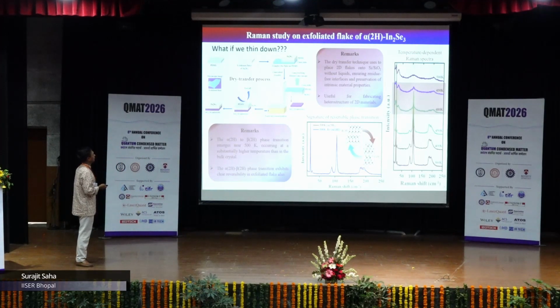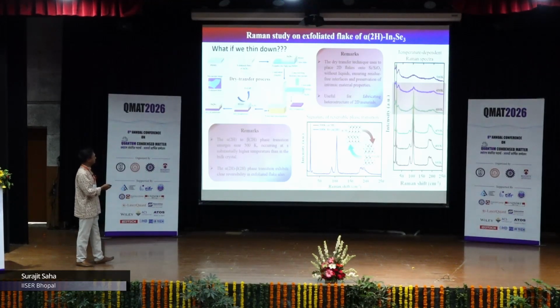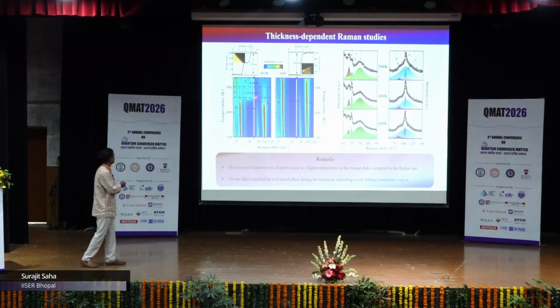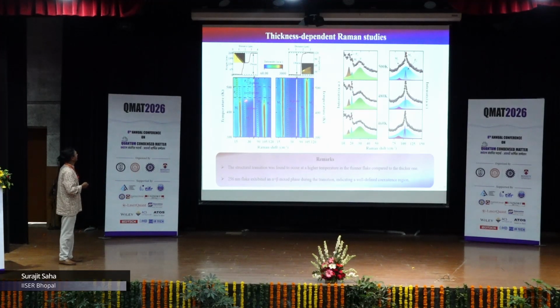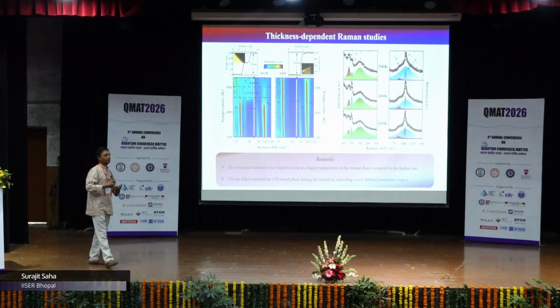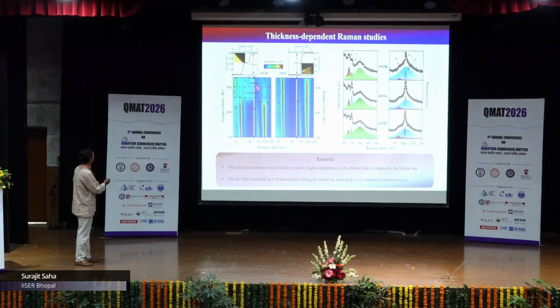So when we thin down, we again relooked at these transitions, and we could see an interesting observation here. I was telling you that the phase transition happens right about 470 Kelvin for alpha 2H to beta 2H, and this is for a very thick film. Of course, everything is very thick, but still there is a significant difference in the thicknesses. This is about a 250 nanometer thick film, where the transition happens somewhere around 470 Kelvin, then there is a slight mixed phase in between,